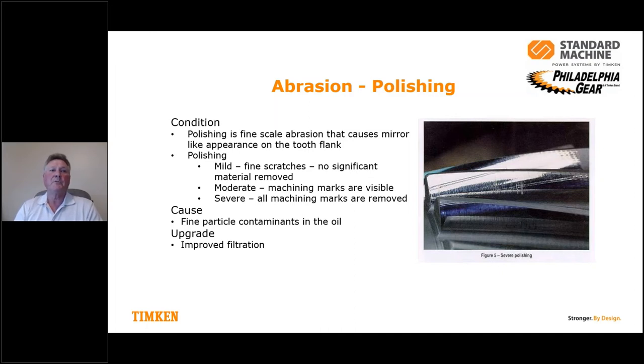For moderate polishing, the machining marks are quite visible. And this would probably be something similar to what that picture is showing you right there. And of course, severe would be all the marks are removed. So it's basically removing a lot of material. So the cause is fine particle contaminants in your oil. If you see this condition, check your oil. It's usually a problem with cleanliness of the oil. And your upgrade is better filtration.